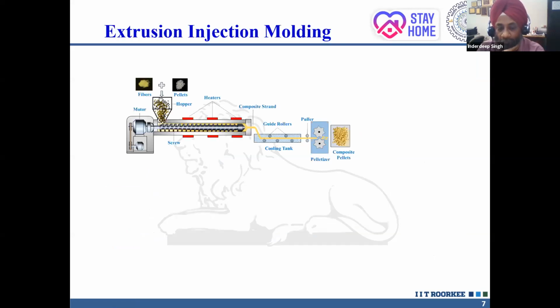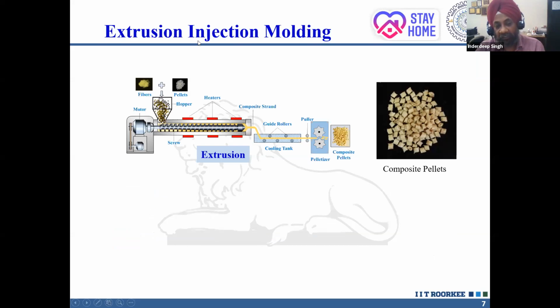Now we have also modified a process slightly. This is the extrusion process. Extrusion also all of you know. So in extrusion, similarly as in direct injection molding, we are putting the fibers and the polymer pellets into the hopper. We are making a batch of this, putting it into the hopper, and then we are compounding the fibers and the pellets together and extruding. So in injection molding, directly a sample is made, but here we extrude a long strand or a composite strand of 4 to 6 millimeter diameter, cool it and then pelletize it. Pelletizing means we cut it. So after cutting, we get the composite pellets like this.